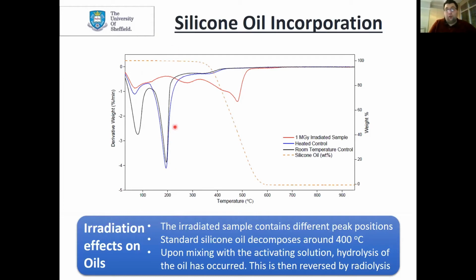This drop at 200, I believe, is due to the hydrolysis of the oil that has occurred within the activating solution. When we've irradiated the sample, this red line, we've actually reversed this reaction to a point and reformed the oil chains slightly. This is why we get this large area of sample that appears to contain oil in this region.